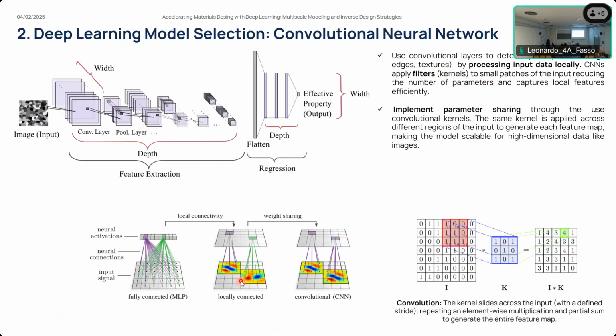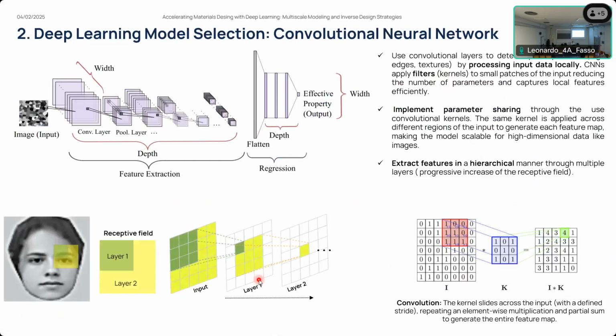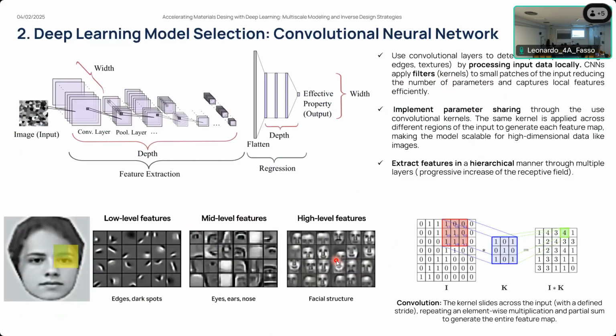Another characteristic of these neural networks is that they implement parameter sharing, which is done through the use of these convolutional kernels. Specifically, we use the same kernel applied to different regions of the input to generate each feature map, and this allows us to have a much more scalable model for high-dimensional data like images. Another characteristic of convolutional neural networks is that they are able to extract features in a hierarchical manner. This can be better understood through this figure, where we observe that the receptive field, which is the portion of the image that affects a neuron in a given convolutional layer, progressively increases as we go deeper into the convolutional layers. The effect is that the neural network is able to extract hierarchical features from low-level features to mid-level or high-level features.